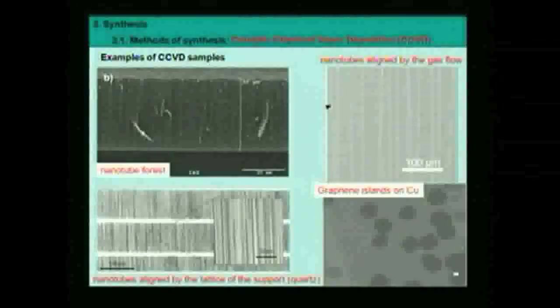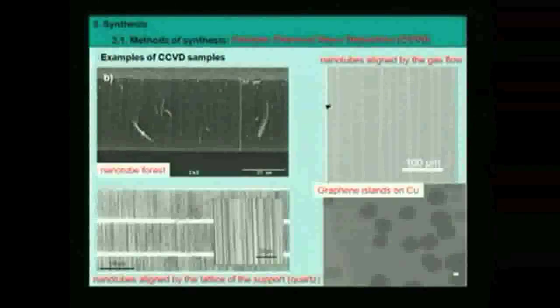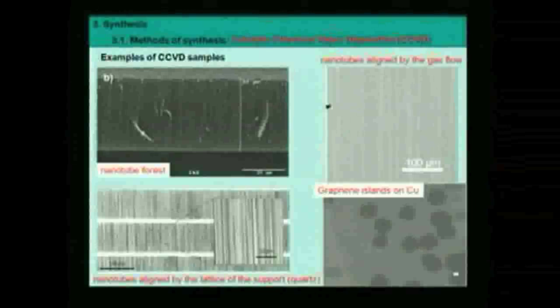Okay. So the question was about the interaction between nanotubes and the substrate, and its effect on the orientation. Is it, does it have an effect on the orientation of the nanotubes? Maybe I can go back to those pictures I presented at the beginning. Here, for those two, the gas flow alignment and kite growth alignment, I already explained. It's a van der Waals interaction in this case with the support. So it's an interaction between the tube and the substrate that causes the alignment. Okay?